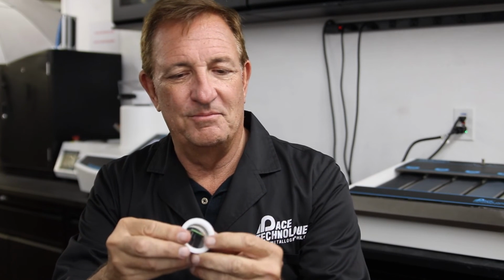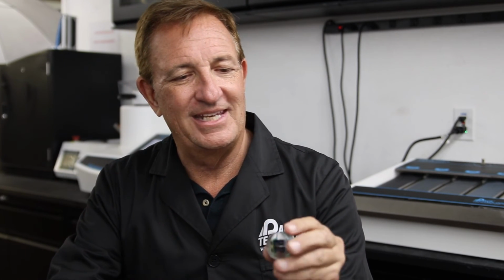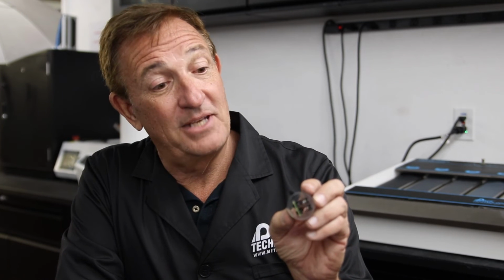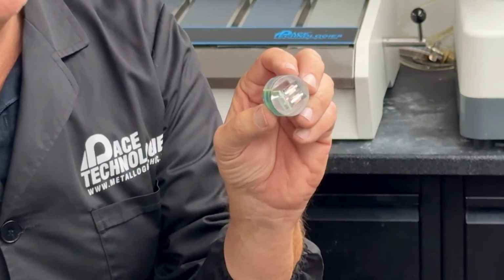And this, let me just pull that apart. And then you just press out your sample here. And here, with this sample, you can see a little bit more detail. This was a couple of capacitors that we had cut in half and then mounted. In this case, it's a good example of why we'd want to use vacuum impregnation, because these wires in here in particular, you see the copper wires, would be unsupported.